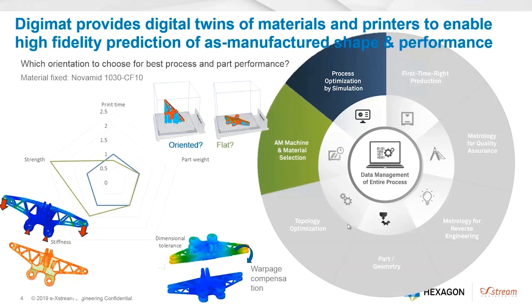Indeed, when we choose the oriented approach, we obtain a stiffness which is twice smaller than for the flat, while the strength is approximately 1/4 of the strength for the flat orientation. Therefore, through this simulation chain, we're able to choose the flat orientation as the best orientation that combines process quality, part performance, as well as optimal print time.